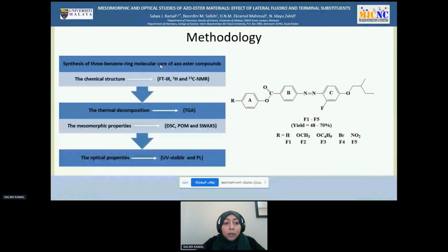Our methodology: synthesis of three benzene ring molecular core of azoester compound bearing lateral fluorine group with 2-methyl-butoxy terminal group on the phenyl azo side, and the second terminal group had either electron donating or electron withdrawing group. As you can see, compound F1 with hydrogen, compound F2 with methoxy, compound F3 butoxy, compound F4 bromo, and compound F5 with nitro. The chemical structure for all compounds was determined by FTIR, proton and carbon NMR. The thermal decomposition was investigated by thermogravimetric analysis. The mesomorphic properties were investigated by differential scanning calorimetry, polarizing optical microscopy, and small and wide-angle X-ray scattering.